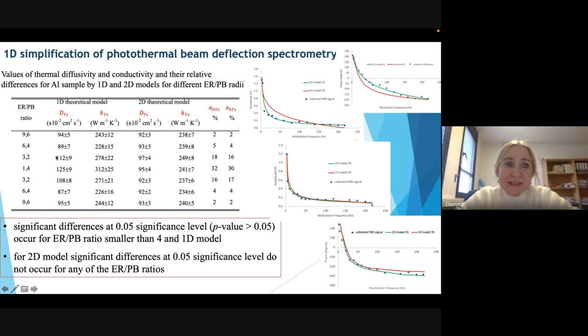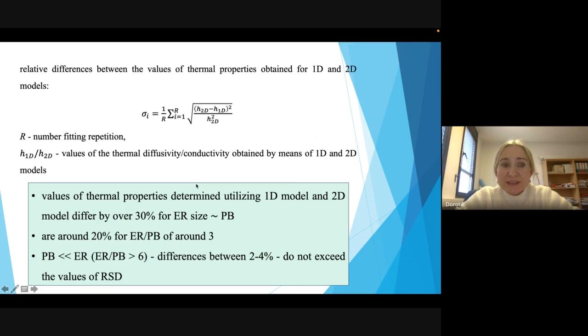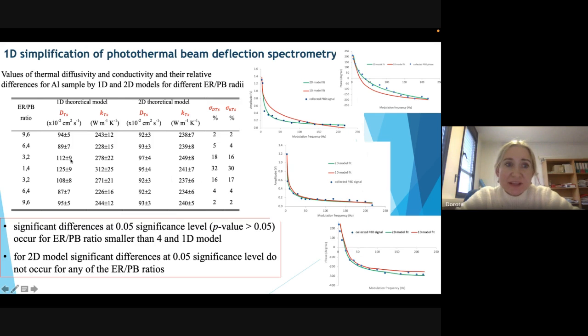Yeah. If the ratio is around 3, they decreased up to 20%. But what is important is that if the ratio is higher than 6, there are no significant differences between the values obtained for the 1D and 2D model. Yeah, and what is more, the differences are at the level of the standard deviation received for the single determination.